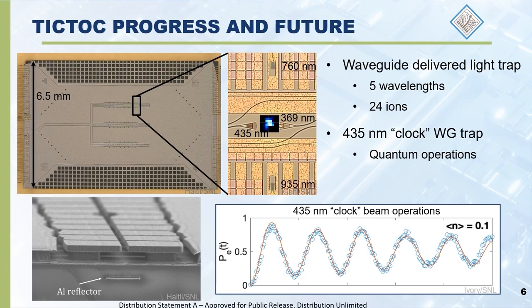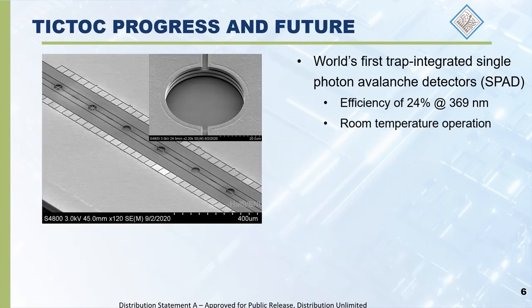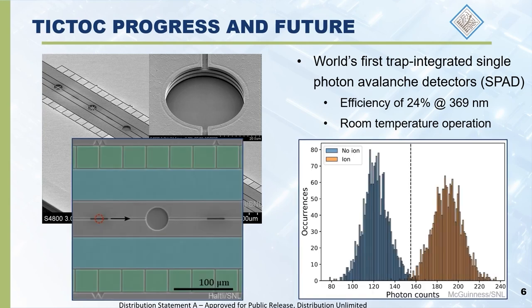In another trap, we've shown quantum operations with a clock laser, proving this concept will allow for correct probing of the ions. We've demonstrated the world's first surface trap integrated single photon avalanche detector, operating at room temperature with an efficiency of 24% at the important ion wavelength, 369 nanometers. We first trap the ion at the location indicated by the red circle and then shuttle it over near the SPAD for better detection.